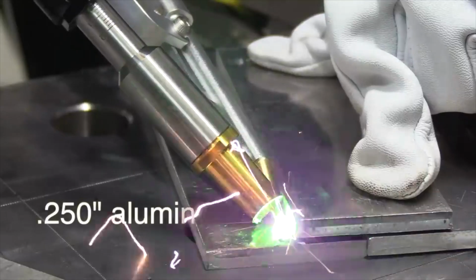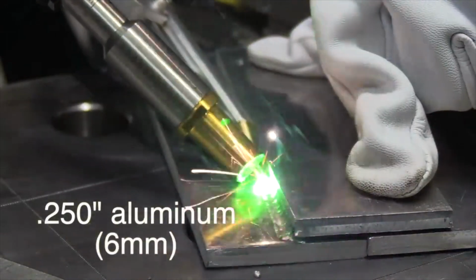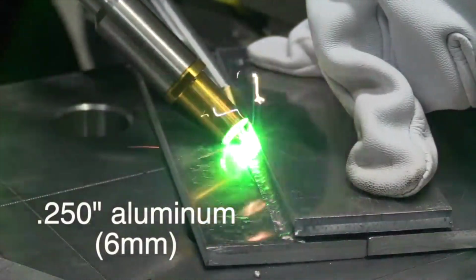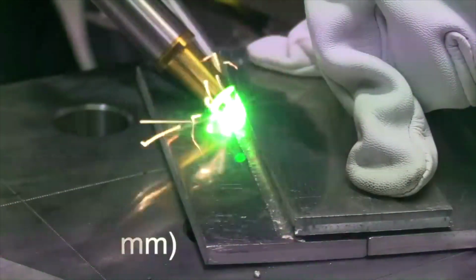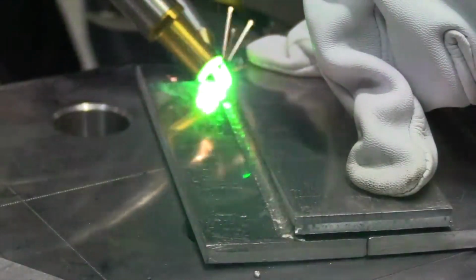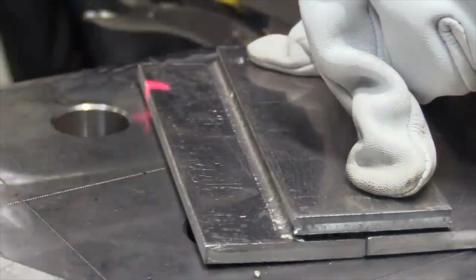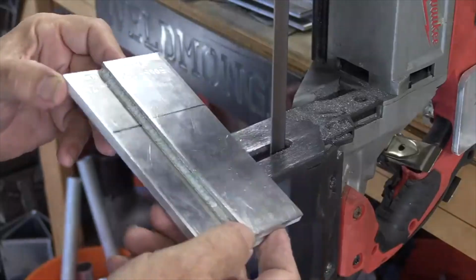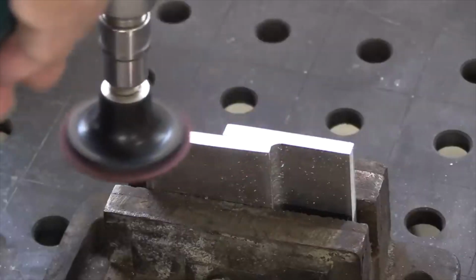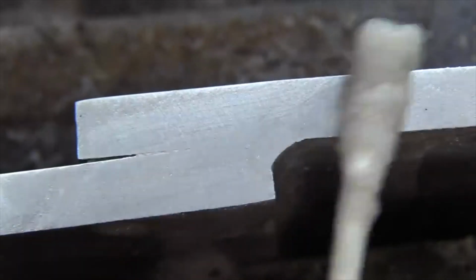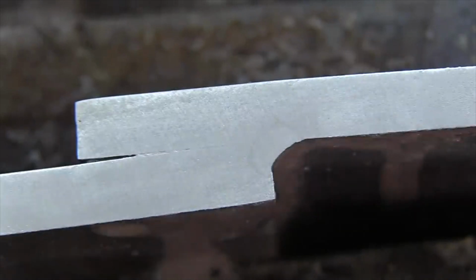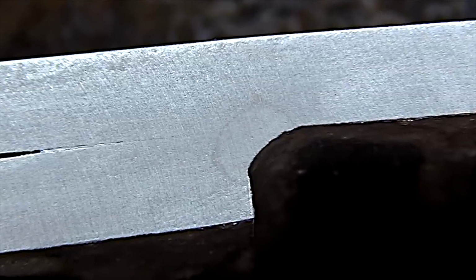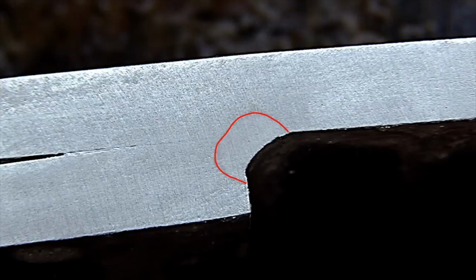There are a lot of skeptics out there when it comes to handheld laser welding, but it is so much faster for certain applications. But is it strong? Is it penetrating, or is it just laying up there like a caterpillar caulk bead? That's a big question everybody has. So I did a macro etch test on this weld, a cut and etch test. After a little polish and a little easy off oven cleaner for etch, you can see that it did get penetration, quite a bit of penetration.